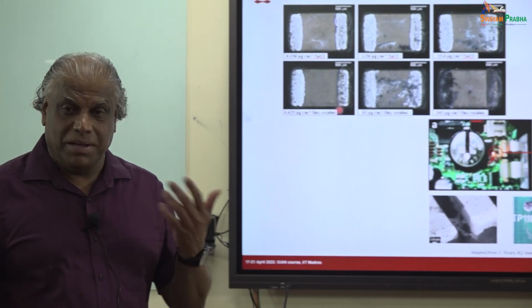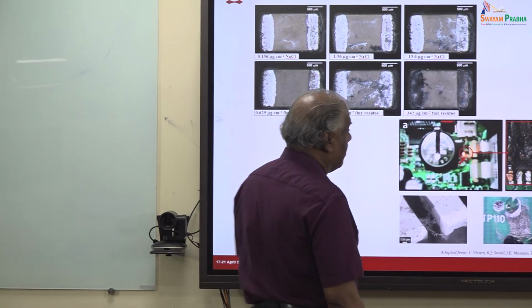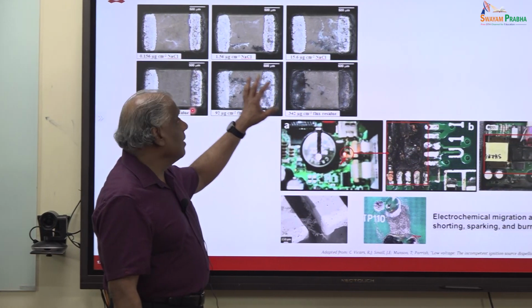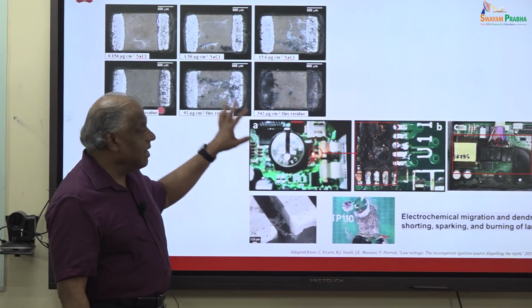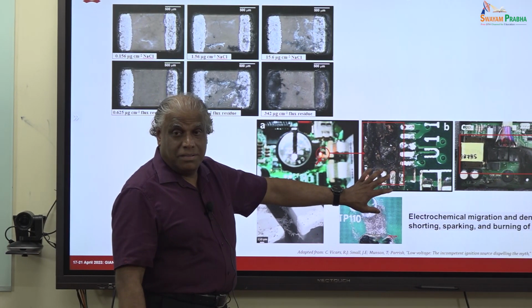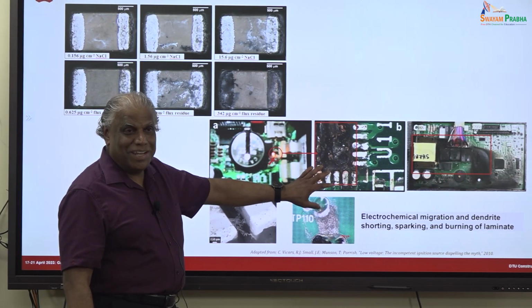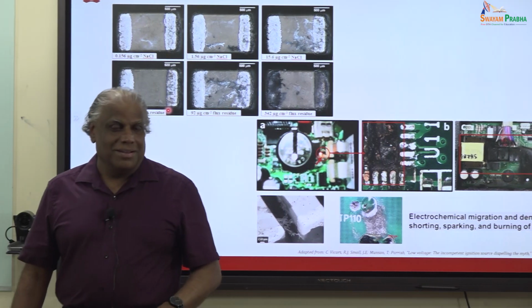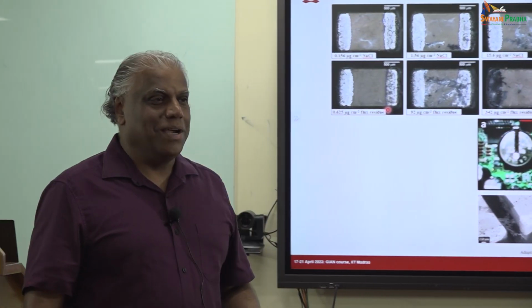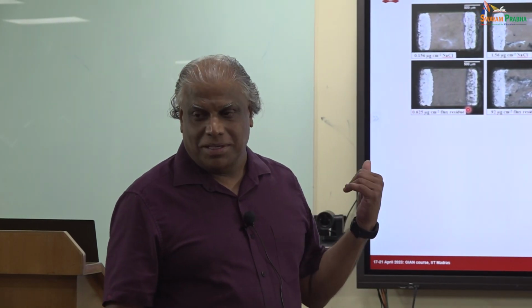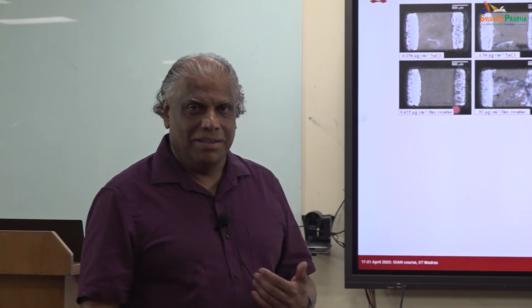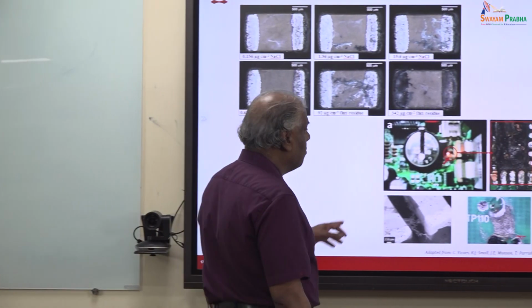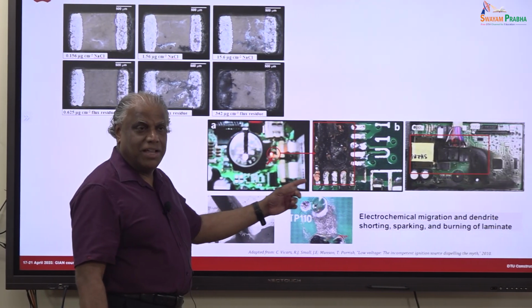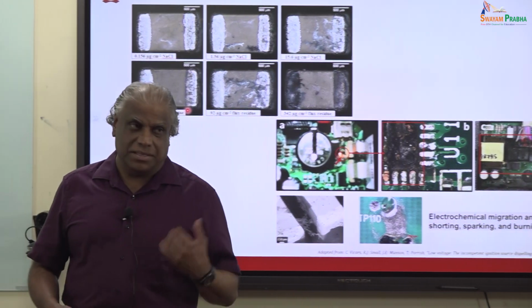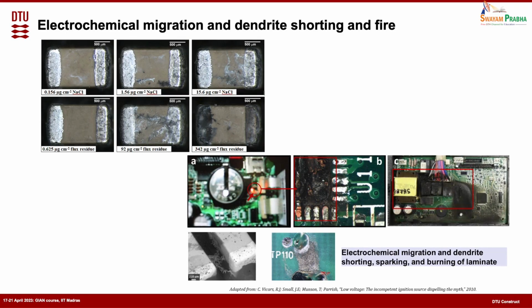Again, coming to the wind turbine failures and automotive failures, this is what happens. It starts with just a water film formation, humidity effects, and ends with a fire. So Bosch also put a name on this failure mechanism. It is called a thermal event caused by a non-thermal event or something like that. It starts with water film formation and has nothing to do with a fire, but it ends up in fire. There are many German automotive companies that lost many cars while transporting just because of this issue. So that is what I'm saying. It's a serious issue, and although it's not always just a simple failure, in some cases it can also lead to such dangerous things.